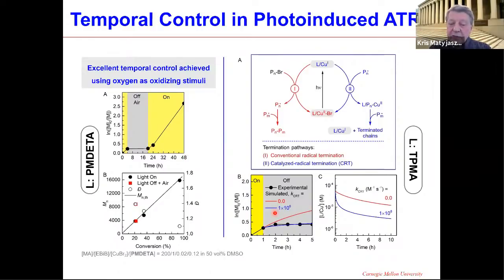So we modeled these reactions, and we found that if we would like to model this dark period with conventional radical termination, the reaction should continue much more than it does. So in fact, not only conventional radical termination, but so-called catalyzed radical termination matters. These copper 1 species are very often extremely active. They can react not only with alkyl halide, but also with radicals, forming organometallic copper 2 species. These are paramagnetic, so they act like radicals, and they can react with another radical and favor a fast termination process. So this is what happens with this catalyzed radical termination process.